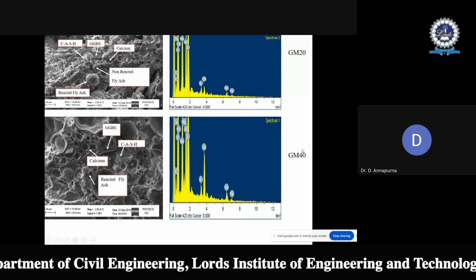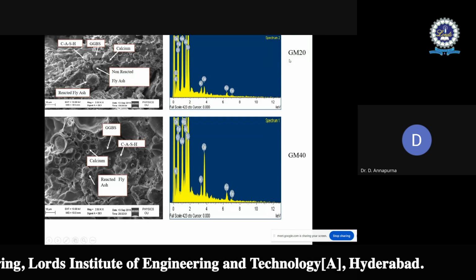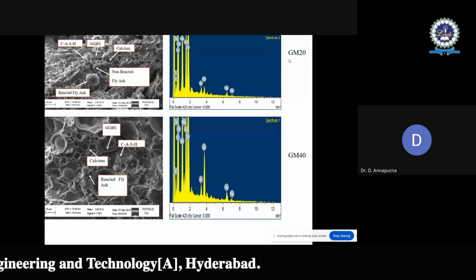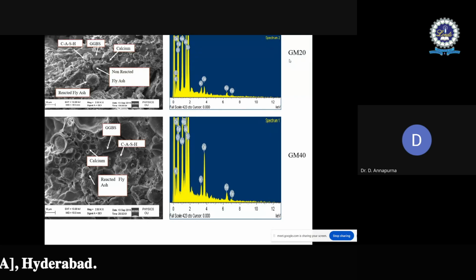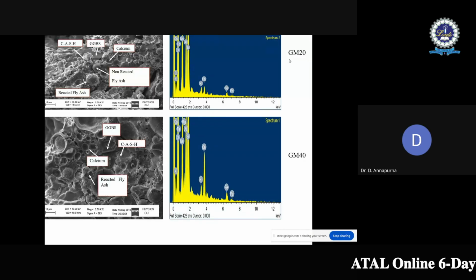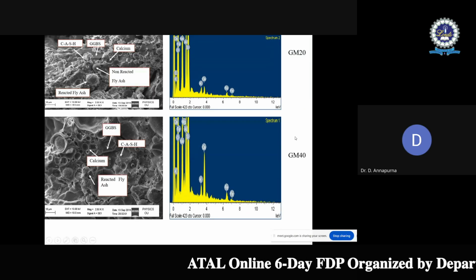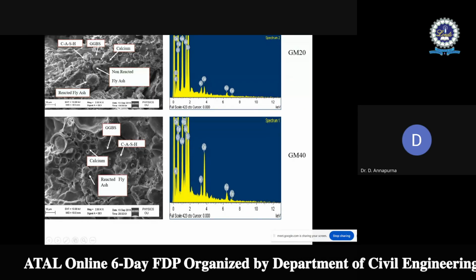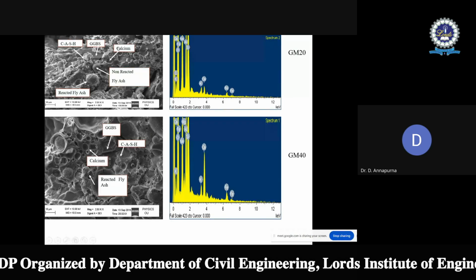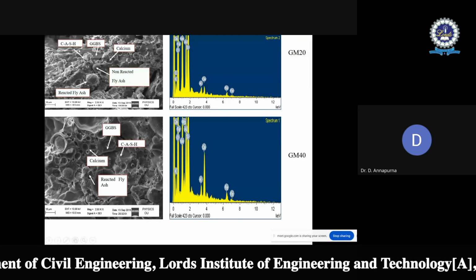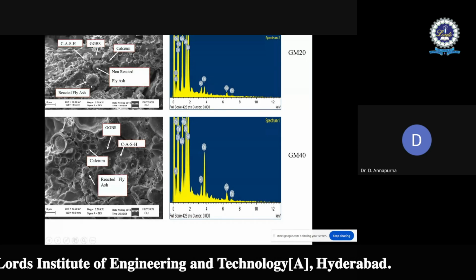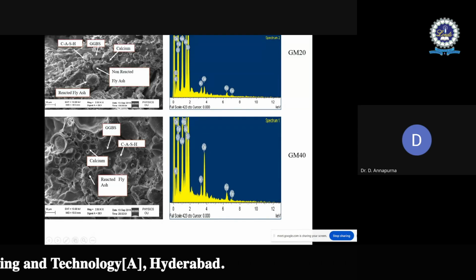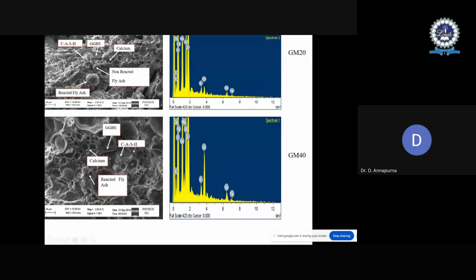Then comes the proposed grades. The proposed grades like GM20 and GM40 are considered. These grades have GGBS dosages. As the GGBS dosage increases, we can see clearly the traces of GGBS, calcium, and CASH gel. Along with the sodium aluminate silicate hydrate gel, calcium aluminate silicate hydrate gel is also seen. This is confirmed through the calcium by silicate ratio.